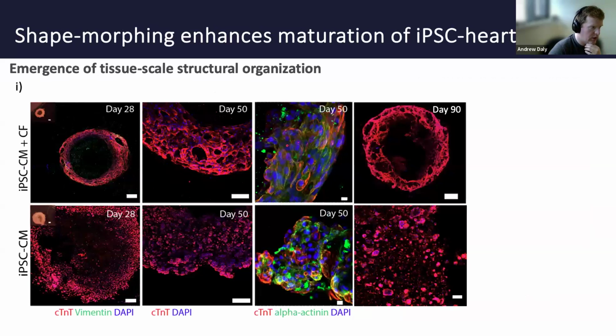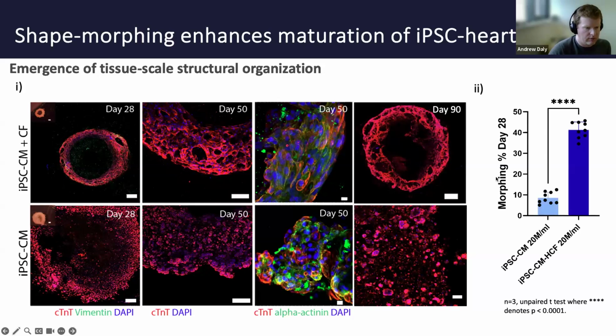And we saw when we looked at the tissues over time and cultured them for long periods of time, like 28, 50 days and 90 days, in this top panel we're looking at structures that shrunk over time when we had a mixture of cardiomyocytes and fibroblasts in the tissue. And we saw, for example, a lot of alignment occurring in that circumferential direction around the tissue. You can really see nice sarcomeres forming. So those are stained by this alpha actinin or green staining here. And so we saw these tubes shrinking when we added fibroblasts.